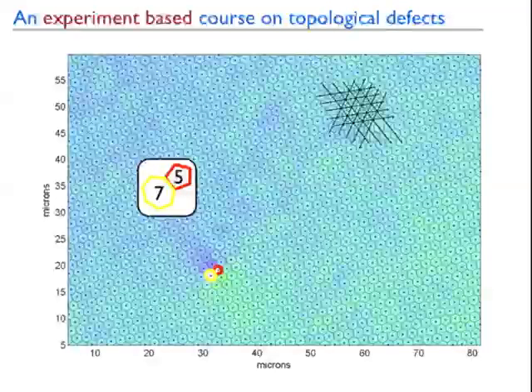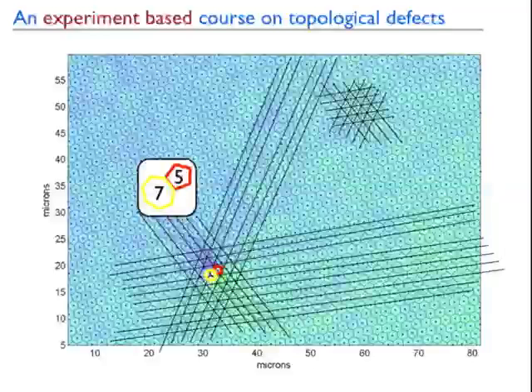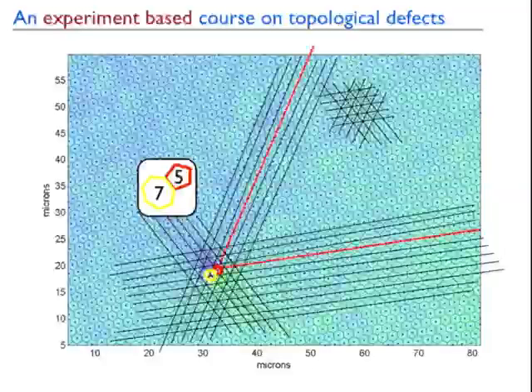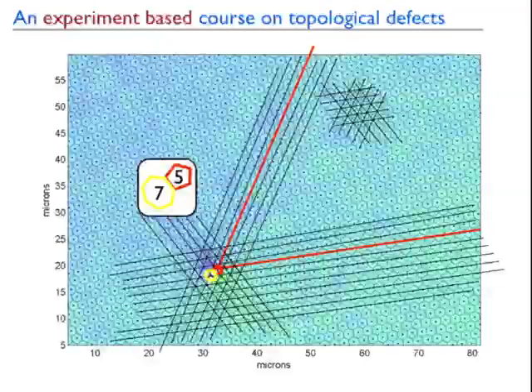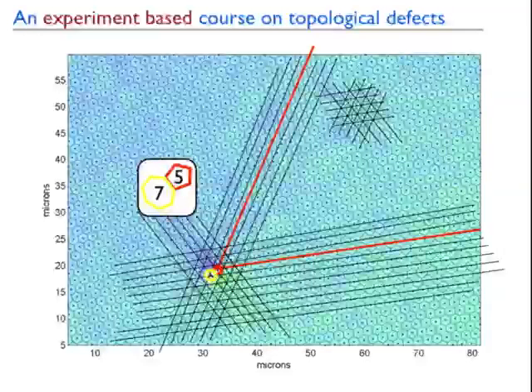You can tell it's a topological defect many different ways. One is what differs over here from the rest of the lattice is here, all particles have 6 neighbors. And over here, this one has 5, and this one has 7. They're called disclinations. The two of them put together make what's called a dislocation. A dislocation in a hexagonal lattice has 2 extra rows of atoms coming out like that. A topological defect is topological because, well, for one thing, it's hard to get rid of. You have to cut the system out to infinity. But it also means that you don't have to see the topological defect to know it's there.